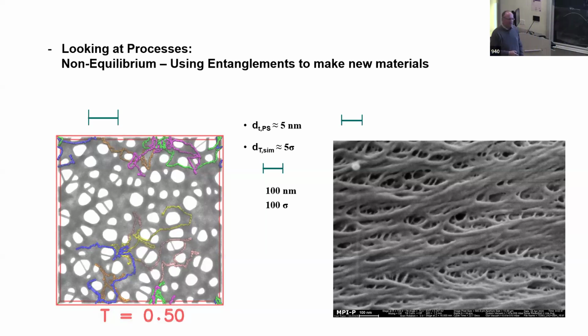So if you wanted to do a negative control experiment and take a polymer and not have it do that, would you just have shorter chains? If the chains are too short, you will get one big hole. So there's a threshold, in both density and chain length. And you need that this is a glassy state. I will come to that in a second. And nothing else special? No adhesive, no links, no loopiness? It's standard, just a polymer melt and nothing else.